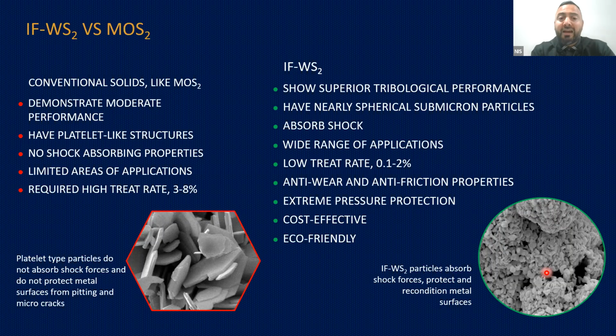Because it doesn't solubilize, it's an actual dispersion. Imagine it's not like sugar in water, it's more like coffee in water. The coffee particle stays in the matrix of the liquid. You're not solubilizing it, you're making it dispersed homogeneously throughout the liquid. And that's what we do. That's our know-how, how to make sure the dispersion is stable, yet particles are there. When you're solubilizing organic matter, like oils and maybe some additives in the oil, it's a totally different mechanism for how those solubilized additives work. When you're not solubilizing, but have actual active material and ingredient in the system, it starts working pretty much immediately. You don't need a sacrificial time period to make the material work and generate tribofilm. I'm going to show several slides on this separately.